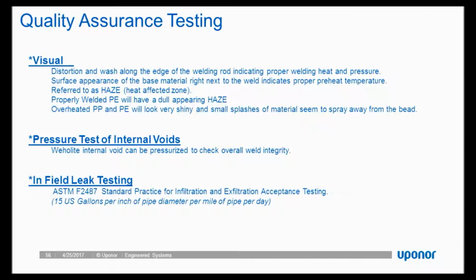Quality control and assurance is very important where thermoplastic extrusion welding comes into play. Our first line of defense is a visual inspection. As I mentioned earlier, a heat-affected zone should follow the weld seam. This would be a dull-appearing haze or dull-appearing polyethylene as that extrusion gun follows the weld seam. If we see inconsistencies in that haze or splashes of material or shiny spots, we did not get a good weld, and we'll have to regrind and reapply that weld to that particular part until it tests.